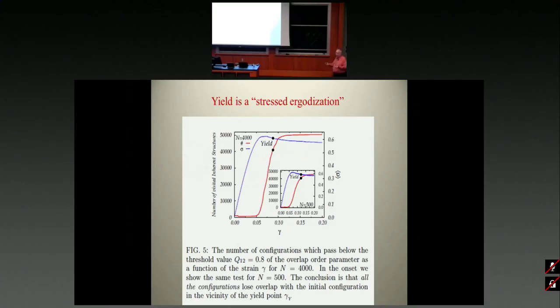And I ask how many of the replica the overlap function has gone below, let's say, 0.8. Okay, arbitrary, can be 0.9, it doesn't matter. And you see that all of them, all the 50,000, I have 100 patches, so 500 each, all the 50,000 lose their overlap around the yield. So this is an opening up, in the sense that all the replica are now seeking life in a huge vista of possible configurations that were not available when you were in the elastic regime.